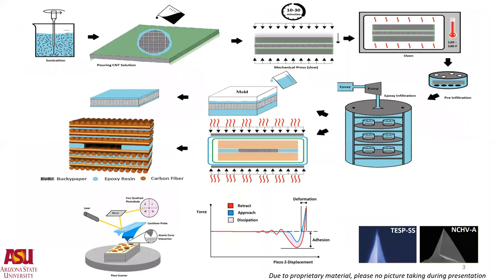This slide shows a summary of the fabrication procedure. It's basically the compression technique that we use for the Bucky paper. The Bucky paper from this technique is infiltrated — essentially soaked with epoxy resin under pressure. The infiltrated Bucky paper is used for two different purposes: one for fabrication of Bucky paper films, and the other for fabrication of three-phase nanocomposites.